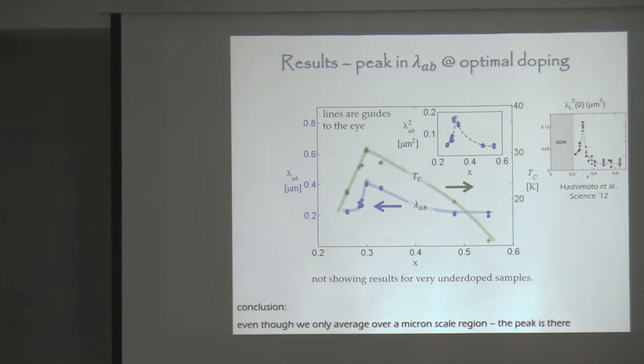So if the sample is not good, we don't care. It's actually better for us because we go somewhere else so we get a different doping. Okay? I'm not showing you very underdoped samples because they're not so homogeneous. These samples are really uniform. You see that you get the same values everywhere.